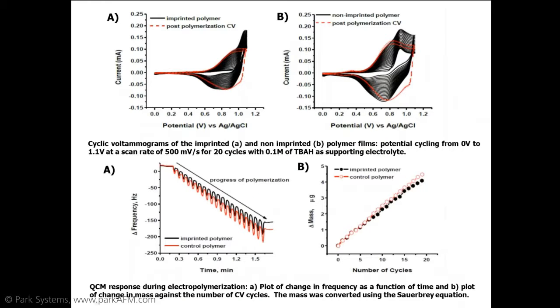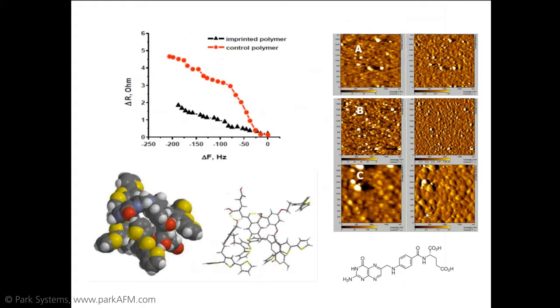The optimization for electropolymerization is done by monitoring the cyclic voltammogram as well as the quartz crystal microbalance trace. So you can see here pretty much we have a linear deposition process. Here you have the monitoring of resistance versus the imprinted or the control polymer. Now, the control simply means that we did not do any molecular imprinting, but simply polymerized the polymer and then tried to do sensor measurements. And here, the complexation ratio for the monomer and the analyte is actually 3:1, as shown in this molecular modeling diagram.